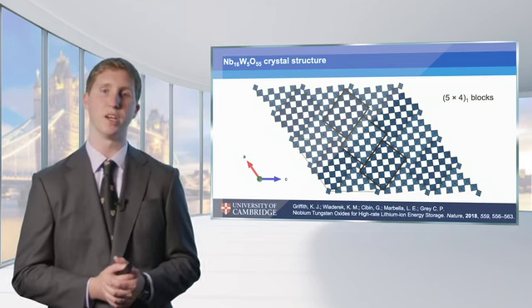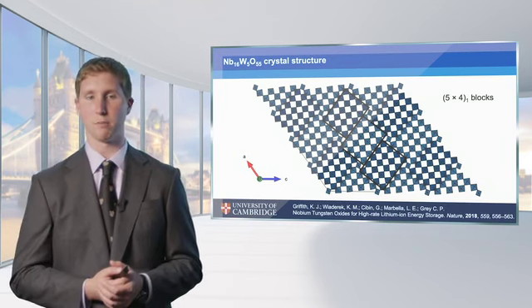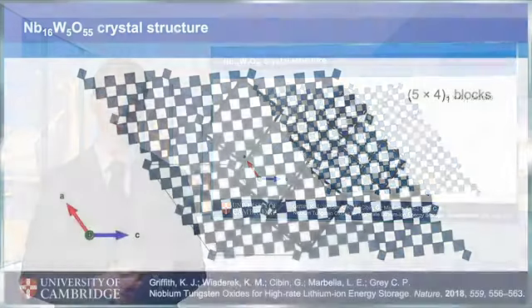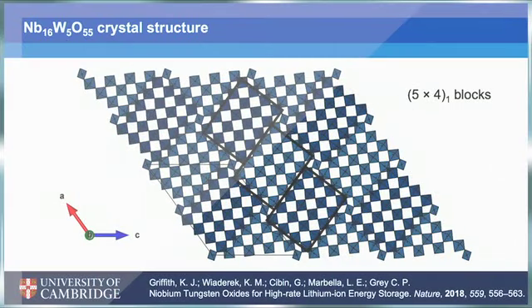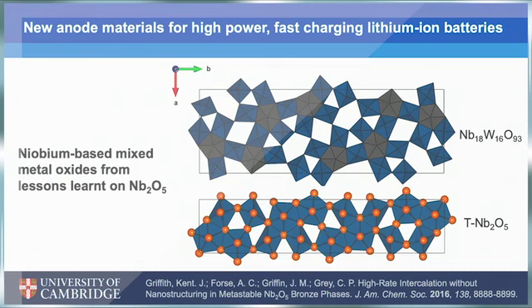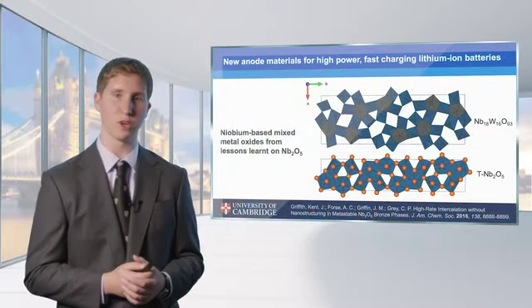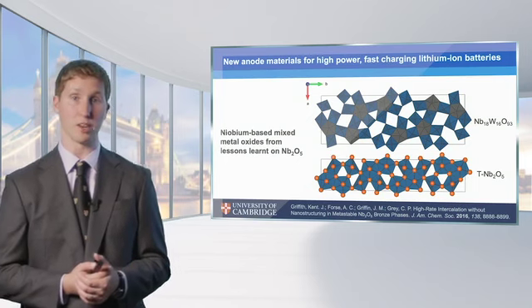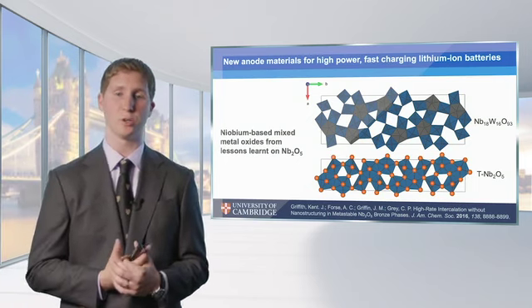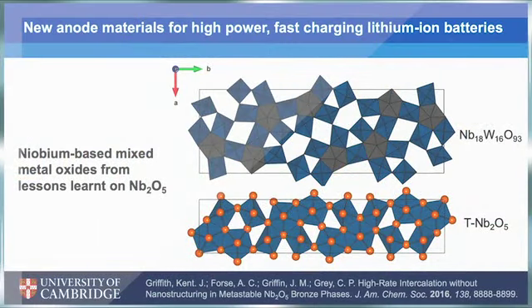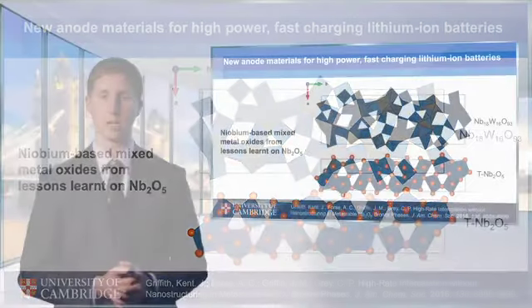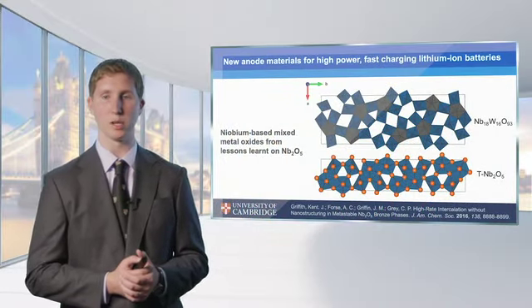is the 16,5 niobium tungsten oxide structure, which, because of the inclusion of around 25% tungsten, has a larger block size. So there's more corner sharing, but you still have these shear planes leading to 5x4 blocks. Now, in addition to the crystallographic shear structures, if you go towards a more tungsten-rich chemistry, closer to 1:1 with niobium, then you actually form a crystal structure that looks bronze-like. And this is very reminiscent of what we see in a low-temperature polymorph of niobium oxide called TNb2O5. And so TNb2O5 itself shows some promising battery performance, somewhat limited capacity, but is a very interesting material. And we actually then can see the comparisons between that and this niobium tungsten bronze.